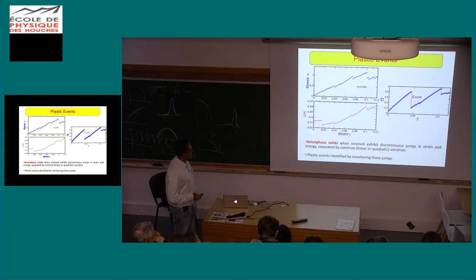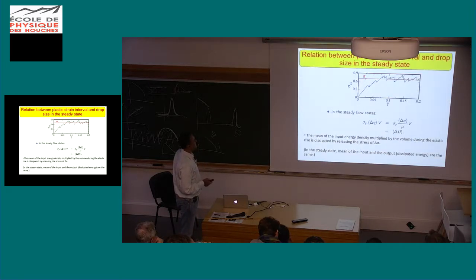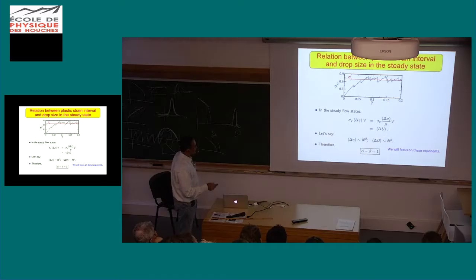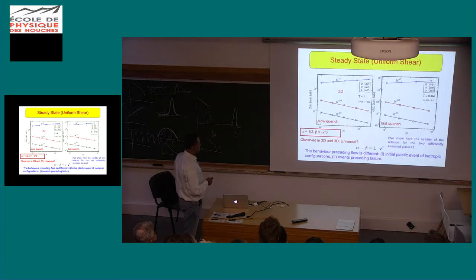Now I want to talk about avalanches. So this is again a familiar picture, and we look at these drops in stress or energy to identify plastic events. And when one such event happens, I'll tell you in a minute how we go about looking at the avalanches corresponding to them. So just to quickly say, this has been looked at a lot in the steady state regime under uniform shear, where one can infer some relationship between the size dependence of the strain intervals or the stress increases between successive events and the energy drops. And this is something that we also find. I won't dwell on this.